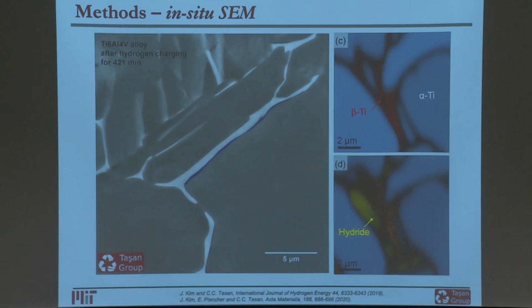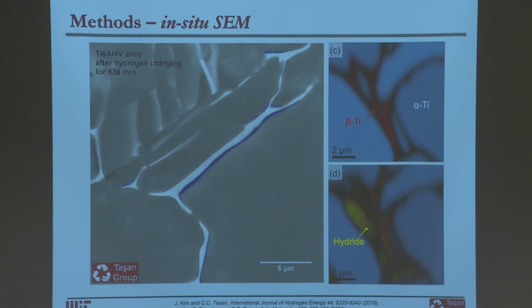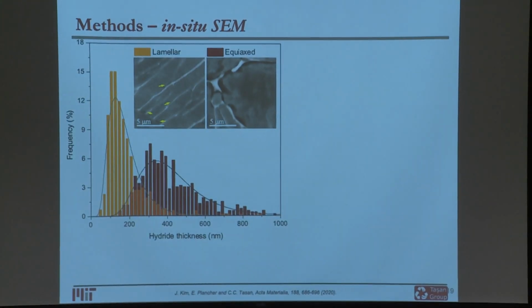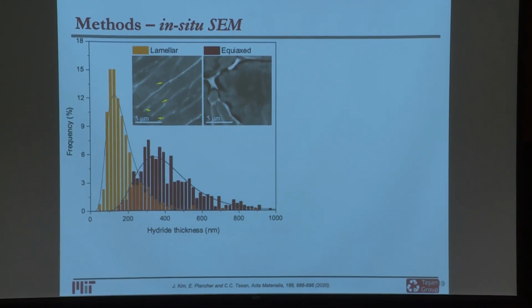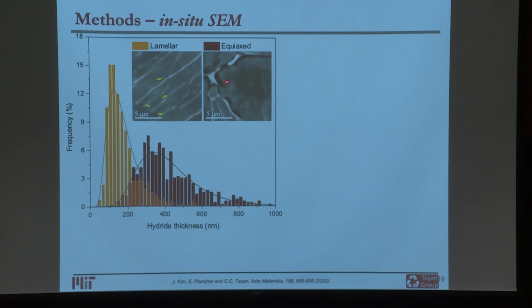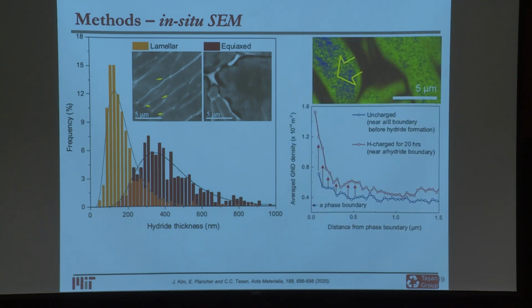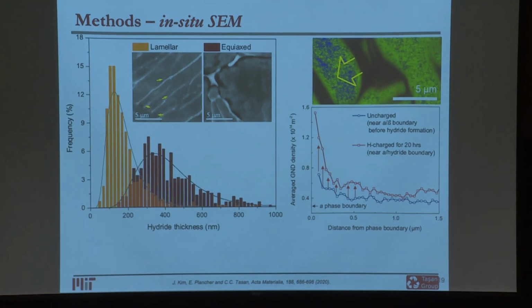And now here in the SEM, we get spatially resolved information, which already shows, if you pay attention to this, that this effect of hydride formation is not very homogeneous. You have thicker hydrides forming in certain regions than other regions. And you can further analyze this data to learn more. One of the things that you learn, for instance, is that if you have these equiaxed beta regions, compared to these lamellar regions, you have thicker hydrides forming. And in fact, it's those thicker hydrides that contributed to failure more significantly. You can calculate defect densities by comparing EBSD measurements before and after too.